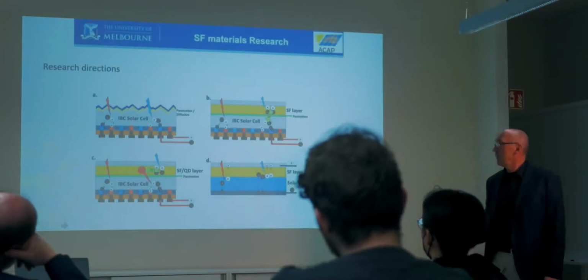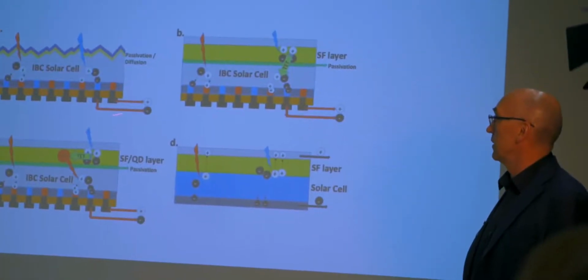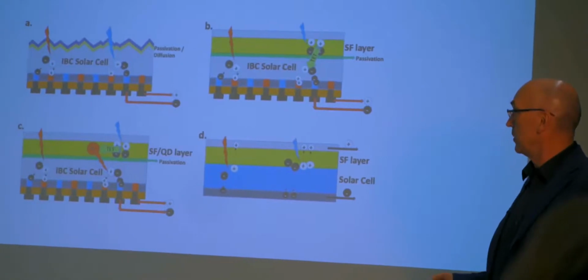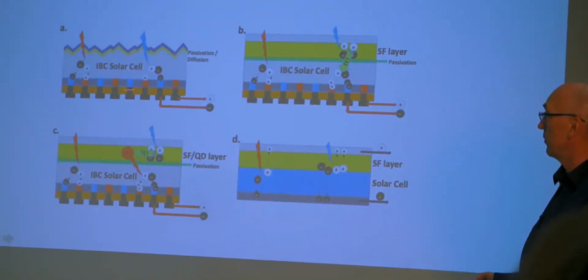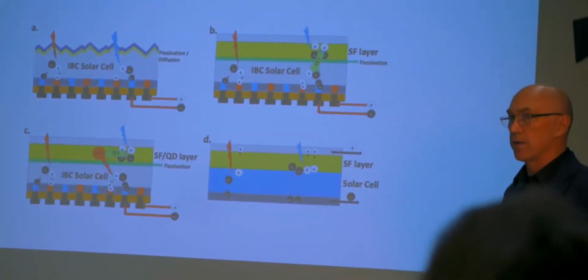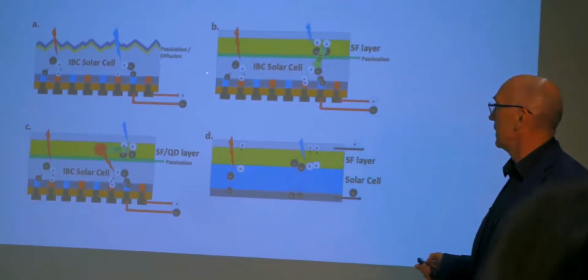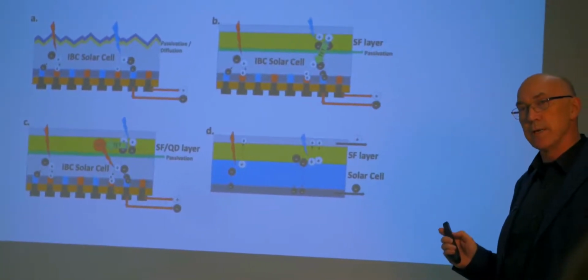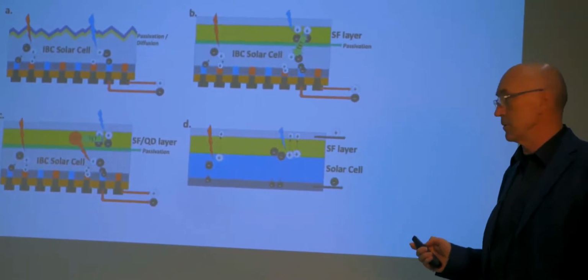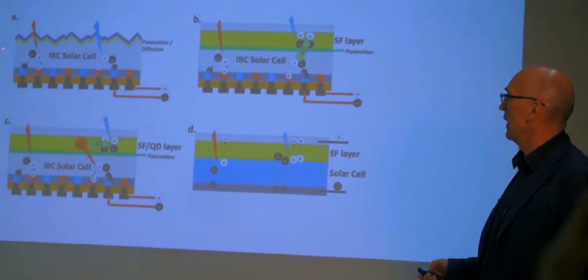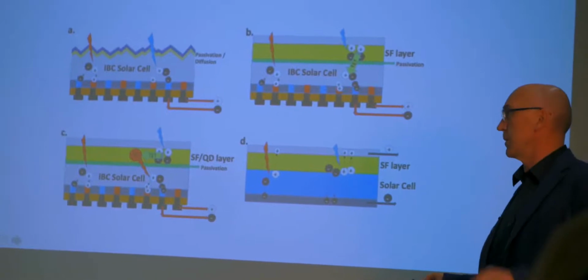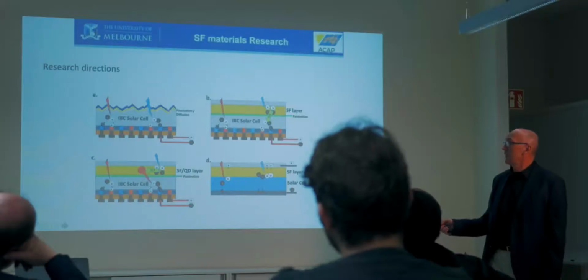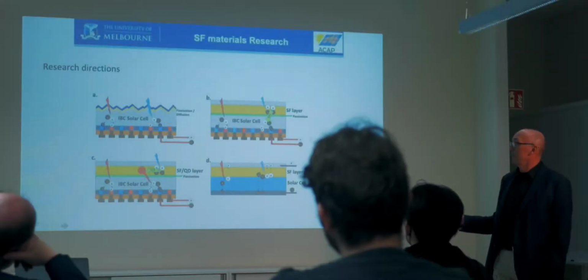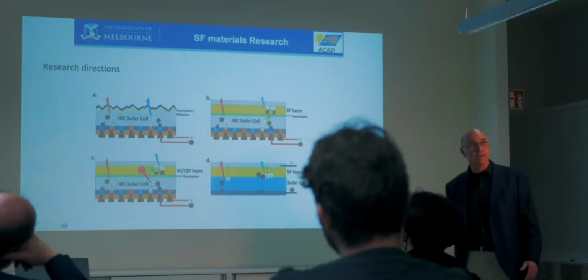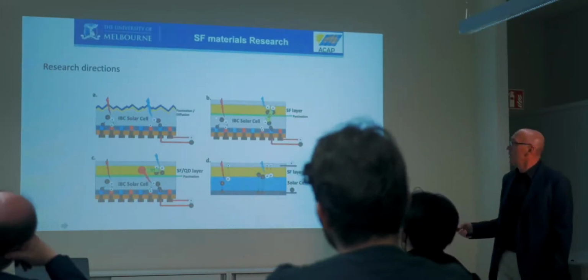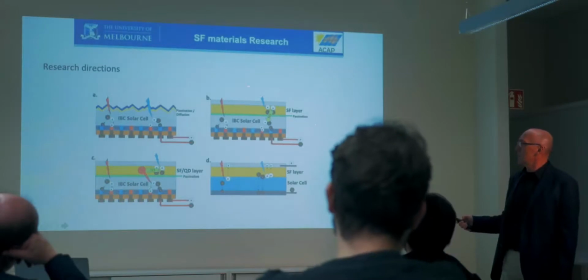If we look at one type of silicon solar cell, this is the interdigitated back contact solar cell, so all the electrodes are at the back, and they have a textured surface for light harvesting. We sit down and say, okay, this is the perfect device for incorporating singlet fission materials, because we can flatten the surface, lose a bit of efficiency, but this is micron scale roughness, and we want a 100 nanometer thick singlet fission layer, so we need to get rid of that initially. So this is the device architecture we're looking at.